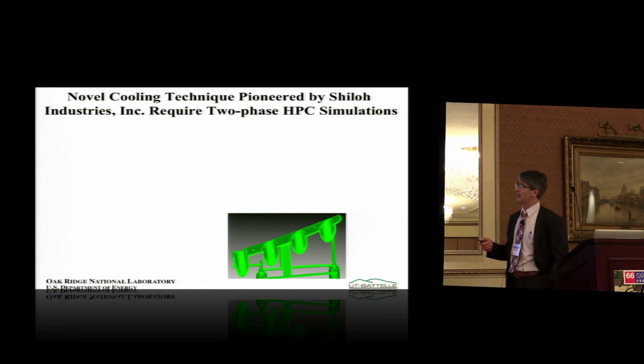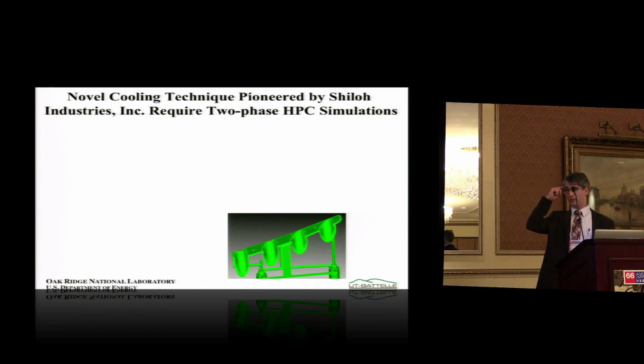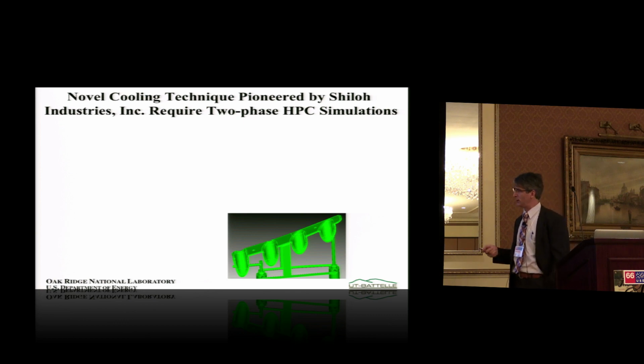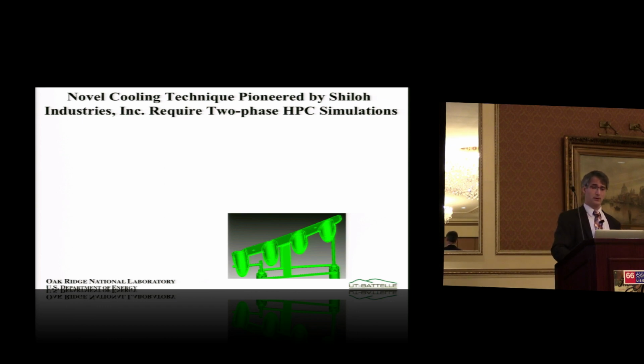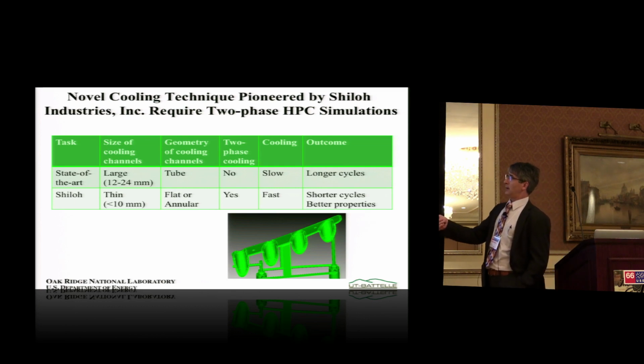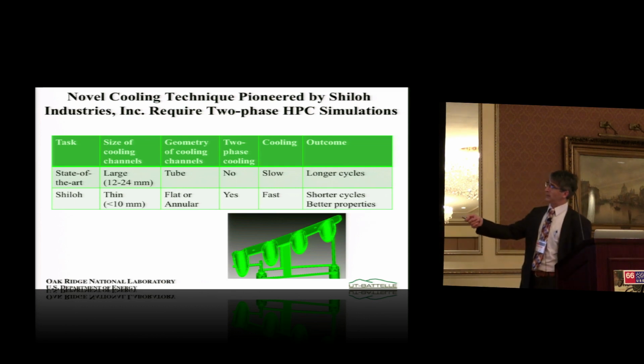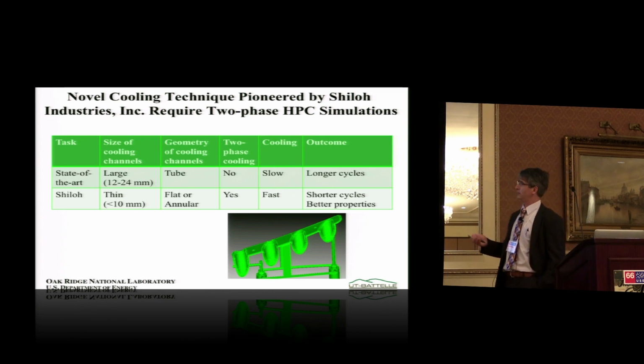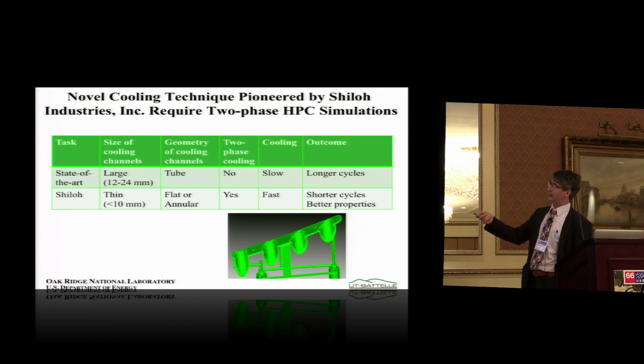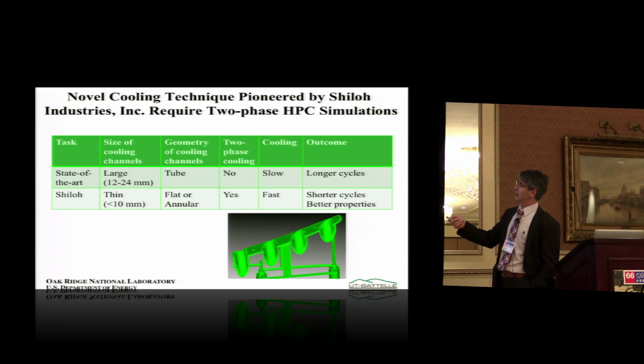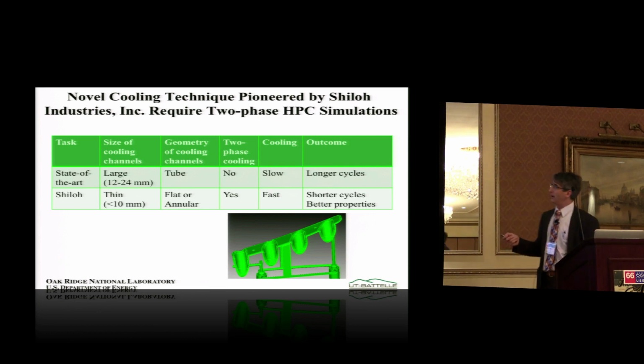And this is a CAD file that I took a snapshot of that was provided to us by Shiloh. And you can see here different cooling passages, and these are some of the new cooling passages proposed. I took the liberty of coming up with this table. You can see in the first line here, what's the state of the art, meaning large cooling channels of a tubular shape with single phase, meaning liquid, cooling, which is slow, and that basically yields longer cycles.